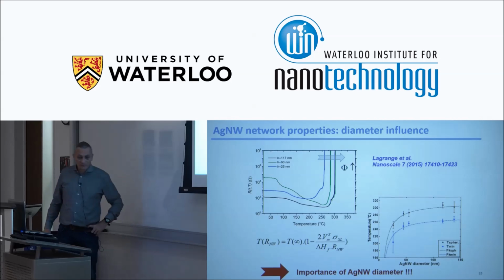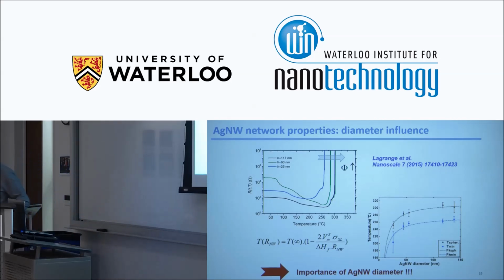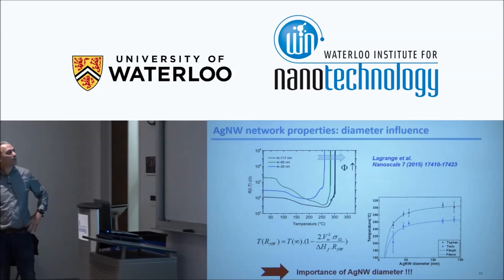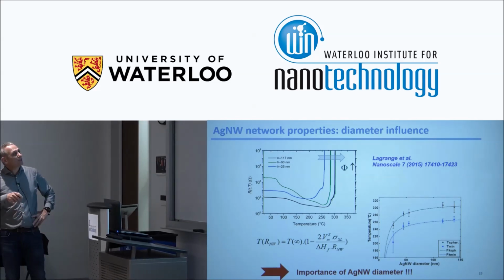These nanowires have been purchased at Seashell Technology in California. And so they were using the same method to prepare them with different nanowire diameters. And we can see that for the lower diameter, the spheroidization temperature is lower, and the minimum resistance temperature is lower as well. So if we plot this temperature versus the nanowire diameter, the red one corresponds to when there is spheroidization, and the blue one when we are optimizing, minimizing the resistance.